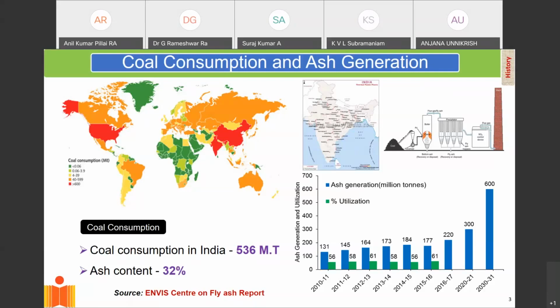The issue that we have is that the coal that is consumed in India is an inferior grade coal. So it basically produces a lot of ash. The ash content of coals tends to be as high as 50%, which means 50% of the coal that I burn is left behind in the form of ash. The average number is around 32%.